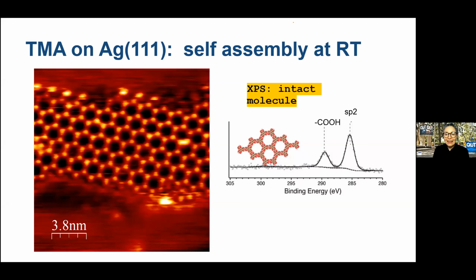We knew based on prior work from Kern's group that if we annealed the surface a bit, we should be able to partially deprotonate the molecule, leading to a condensed phase which is held together through ionic hydrogen bonding. And in fact, that's precisely what we saw. So following annealing at 155 degrees Celsius, XPS tells us that the molecular overlayer is about 25% deprotonated, which leads to this condensed ionically hydrogen bonded phase. So reacted, then self-assembled.